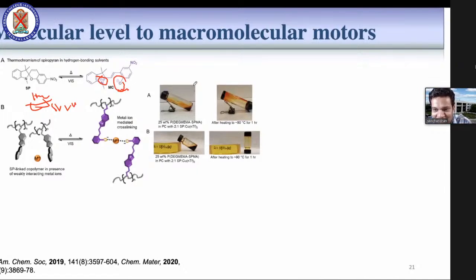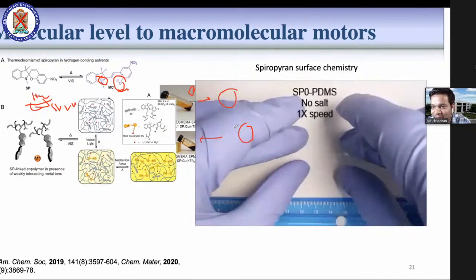So initially, you can have a liquid. When we heat it to high temperature with the bivalent metal ion, you can create a gel structure, which creates a non-covalent structure. It's not a covalent structure, it's a non-covalent cross-linking compound. If you keep it at room temperature in a dark room, it goes to the liquid state. I will show you how it works in mechanophores.